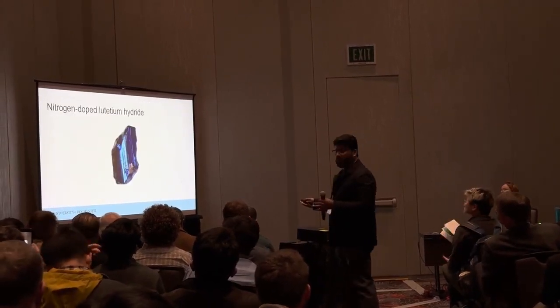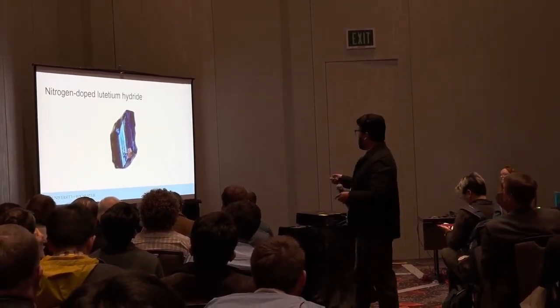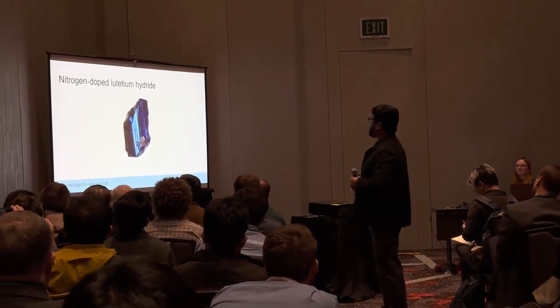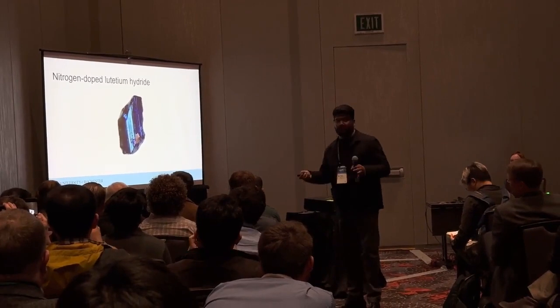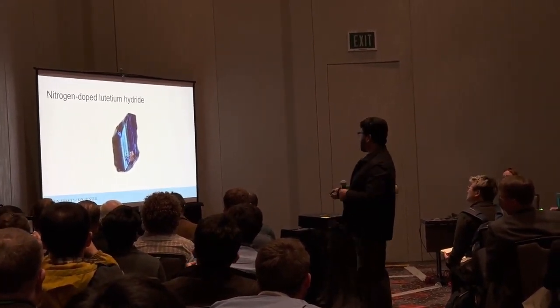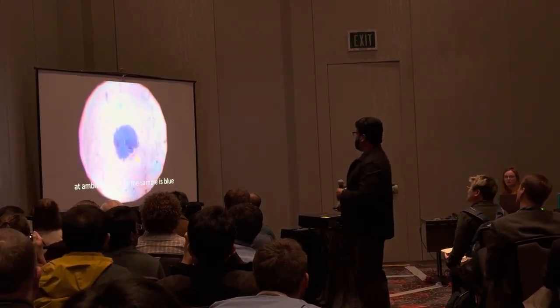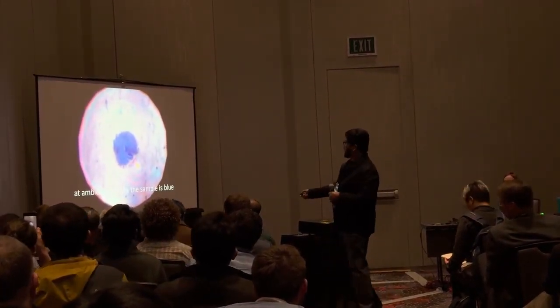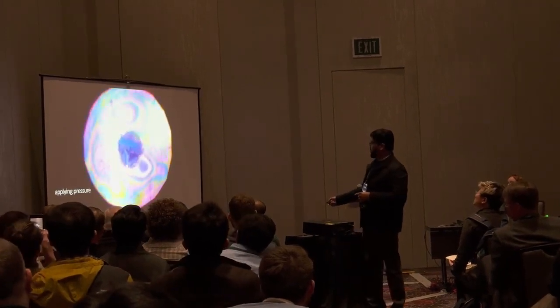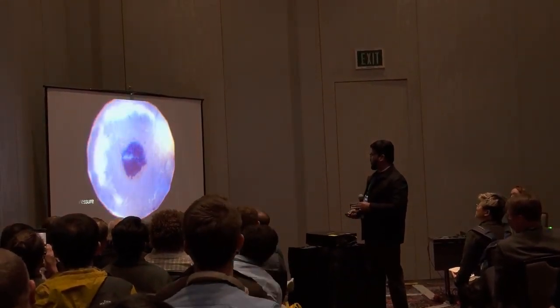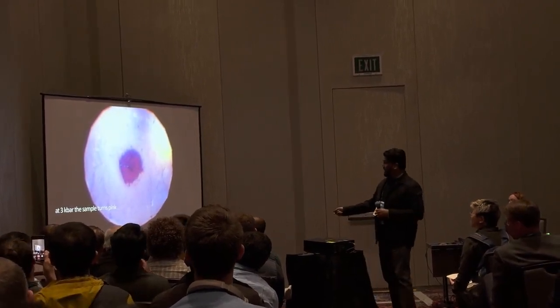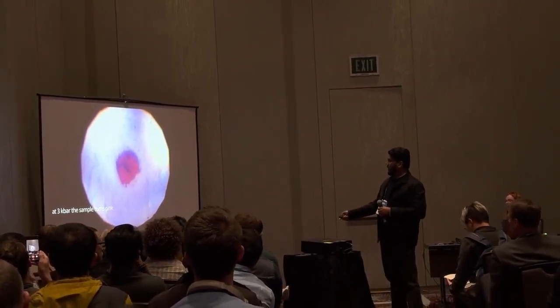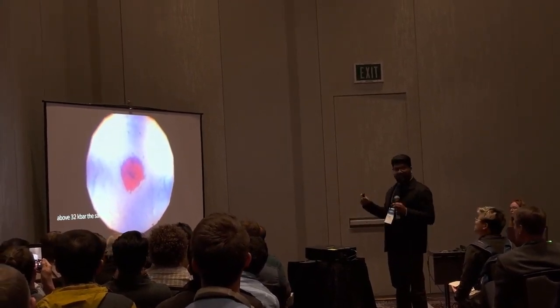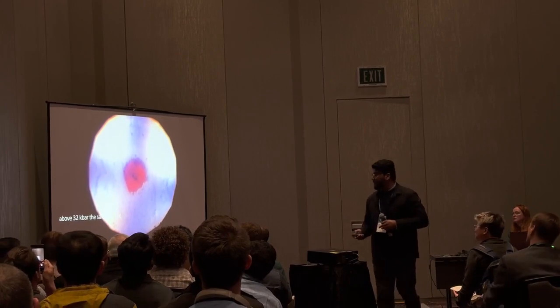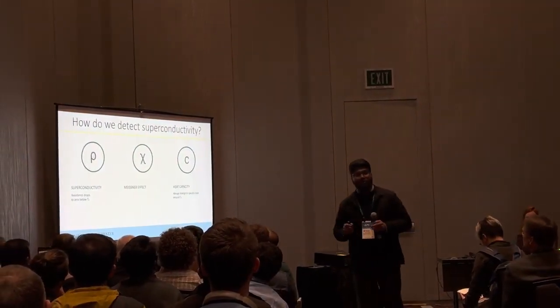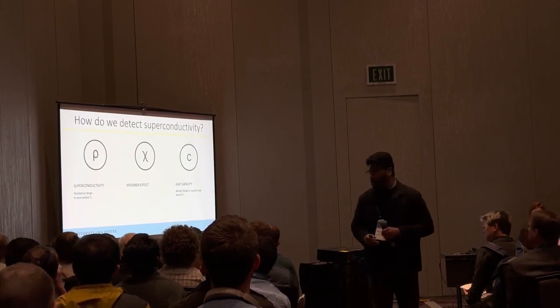So I'm going to introduce a new material for the first time. We have another rare earth hydride called nitrogen doped lutetium hydride. It's a lutetium hydride doped with nitrogen. This is a blue color sample at ambient condition. But if you apply pressure, so start with the blue, apply pressure about 3 kilobar, it turns into a pink. It's a very bright pink color. And then if you further squeeze it, it becomes bright red. So this remarkable material shows the superconducting properties when the color changes from blue to pink around this pink region.